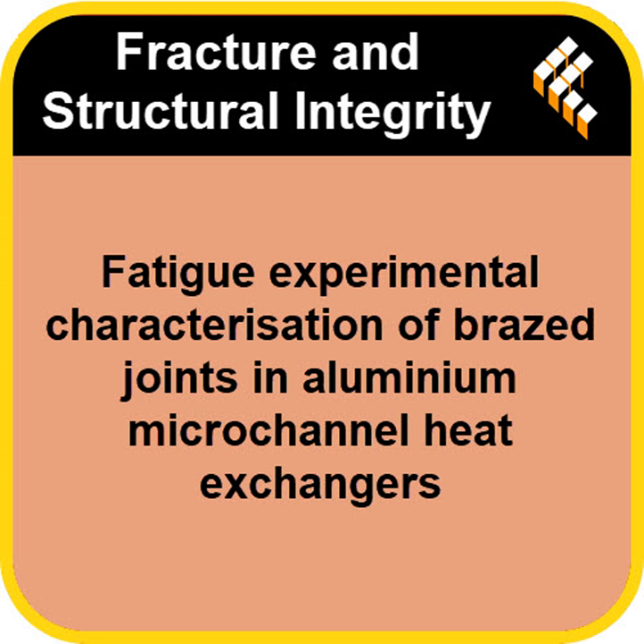The researchers, as we discussed, had to use that conservative FEA model with the sharp corner assumption, the stress singularity. Right, the mathematical idealization. Which means the true, actual, local stress value right at the microscopic point where the crack initiated on that flux inclusion. Yeah. Well, it's still technically unknown. The model points to the location, but the idealized infinite stress isn't the real number. That's correct. It's the engineer's perpetual challenge, modeling reality versus the necessary simplifications.